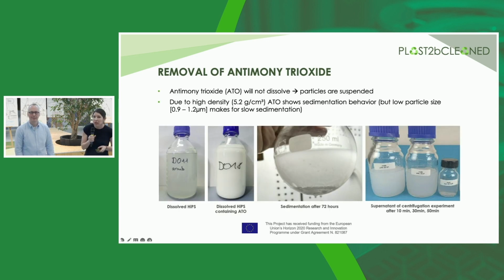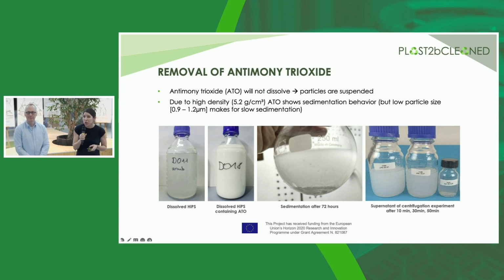For the antimony trioxide, we relied on the fact that particles do not dissolve in the selected solvent and remain suspended in the solution. And because of their high density, ATO shows sedimentation behavior, as you can see on the pictures. So on the left-hand side, we have dissolved HIPS solution and HIPS containing ATO. You can see the milky white solution when ATO is present.